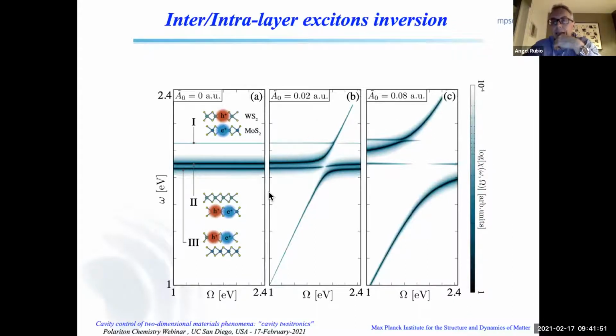In the weak coupling regime, what is expected is that those modes get slightly split, as we wrote in the cartoon before. And this splitting is proportional to just the coupling constant, which is proportional to A0. However, when the splitting is large, you start to get mixed character, and an appearance of, again, new states. Let me highlight what is happening. Before you had these intralayer states here, and then all of a sudden, the intralayer state of the upper material goes up in energy, and then the interlayer state goes in the middle.